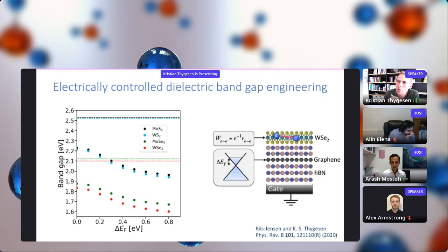Right. Also getting just the different stacking configurations, right? This is all dominated by van der Waals interactions, and different stacking configurations can have energies that differ on a few meV energy scale. So getting that correct and predicting the most stable stacking configurations in general, not just for the twisted, but also for the lattice aligned heterostructures and homostructures is also quite a challenge if we talk about structural properties.